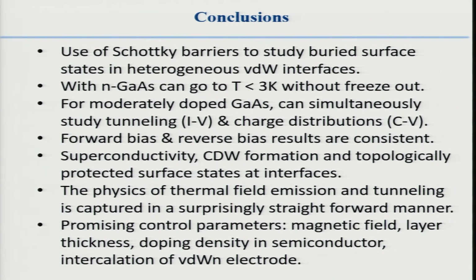We've studied superconductivity, CDW formation, and we'd love to study in more detail the topologically protected surface states and interfaces. We've addressed the physics of thermal field emission and tunneling and captured it in a surprisingly straightforward manner by using the thermal emission equation with the modifications of the eta and Schottky barrier height parameters.